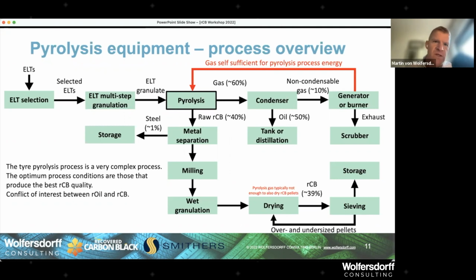Some companies, for specific processes like the dripping bed tower process at Pyrum in Germany, require very small beads so that they can flow. They actually roll down the tower on the heating surfaces. Then you need a small granulate. And of course, the smaller the granulate, the higher the specific surface, and the easier you can heat the granulate. The worst case for heating an end-of-life tire is if you want to pyrolyze a whole OTR mining tire, 4 tons of rubber chunk with metal, and you don't break it up in small pieces. That will take a lot of energy and a long time for the pyrolysis.